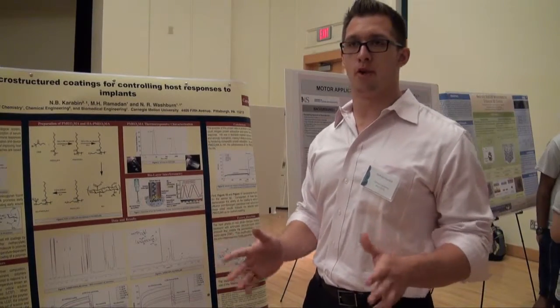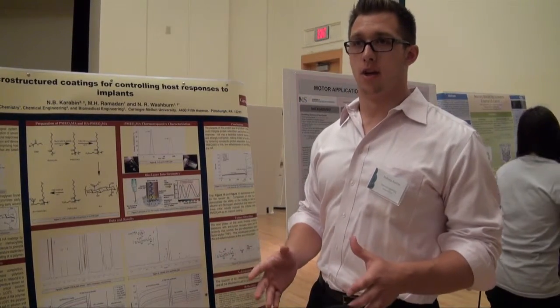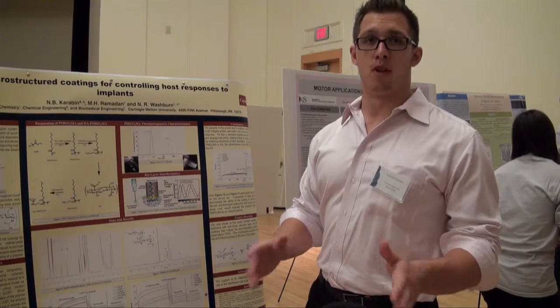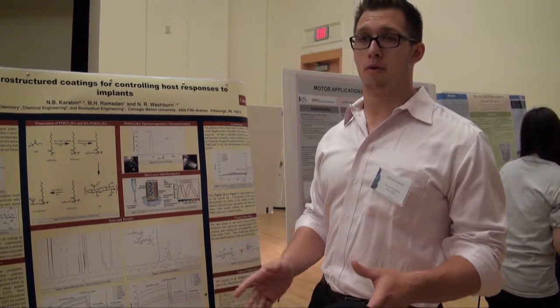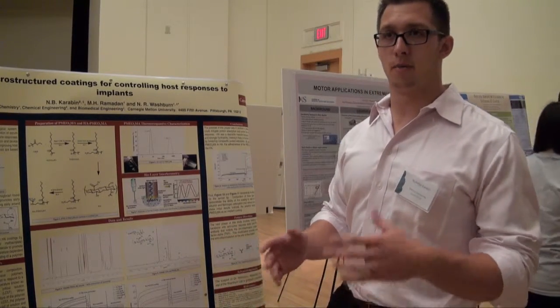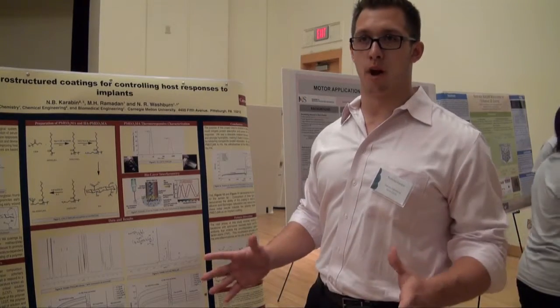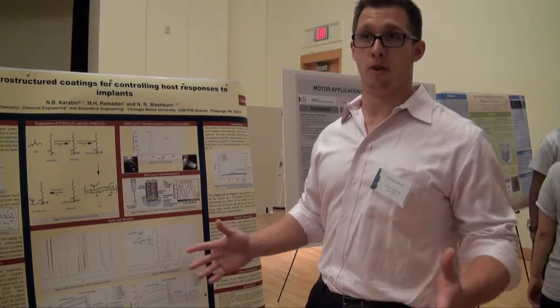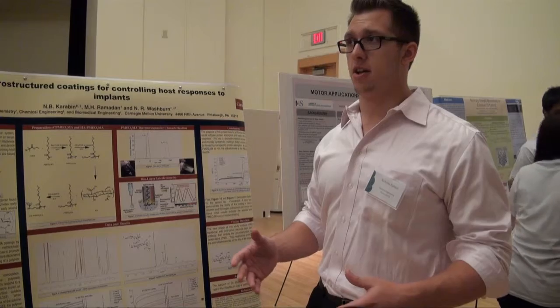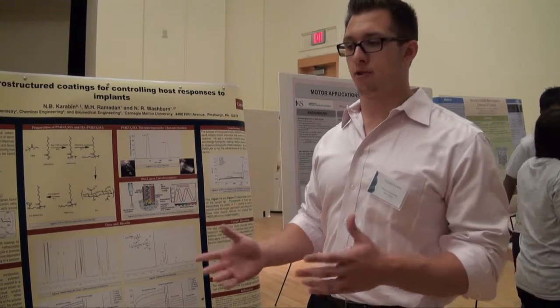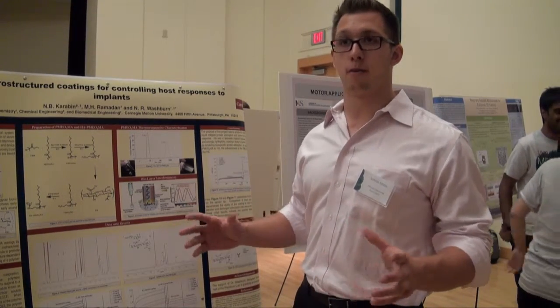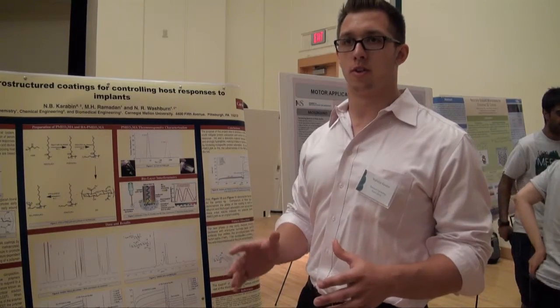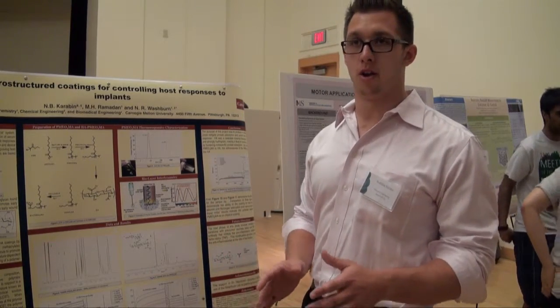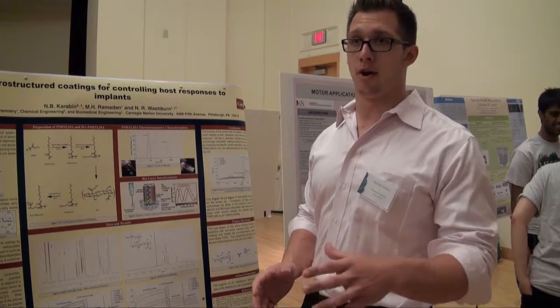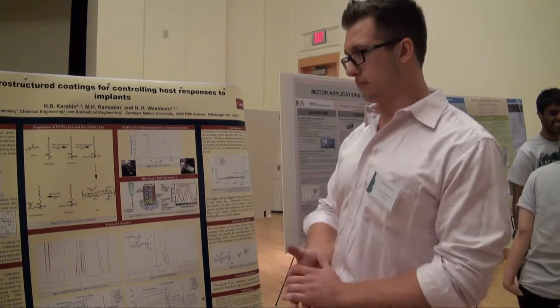So basically the primary issue is when you have an implant, there's going to be some type of immune response from the host. It's particularly so whenever you implant something that's hydrophobic. If you're implanting this hydrophobic material that hates water, and you're in an aqueous environment due to the human body, it's natural for the proteins that flow around this implant to adsorb onto the surface to put a protecting barrier to protect the hydrophobic area from this aqueous environment.